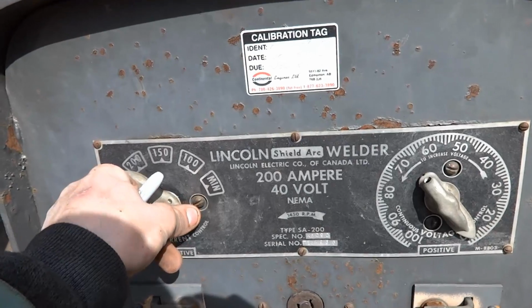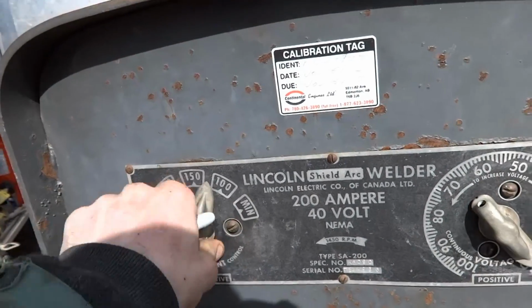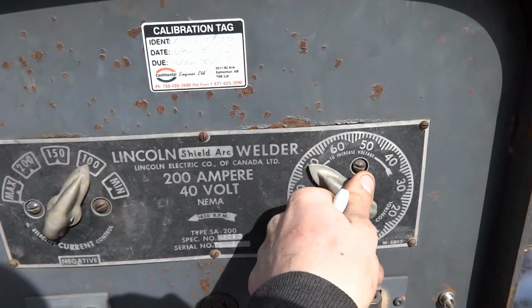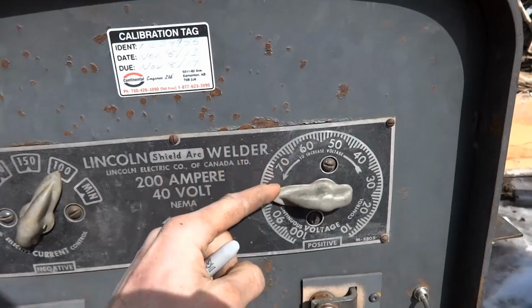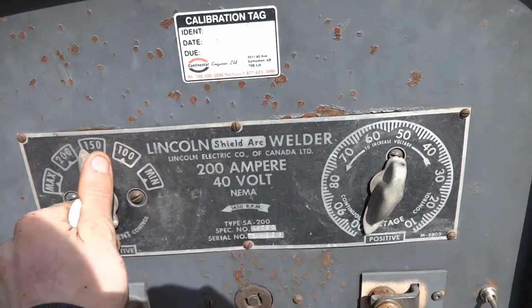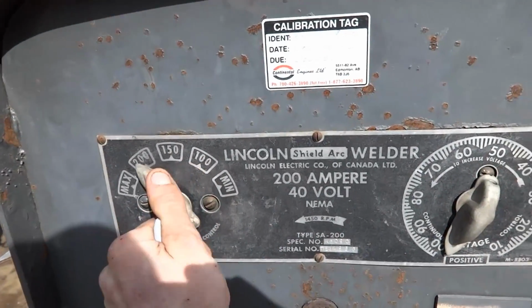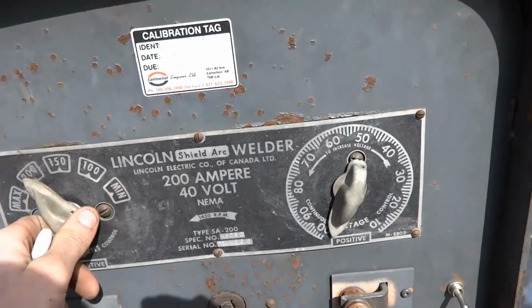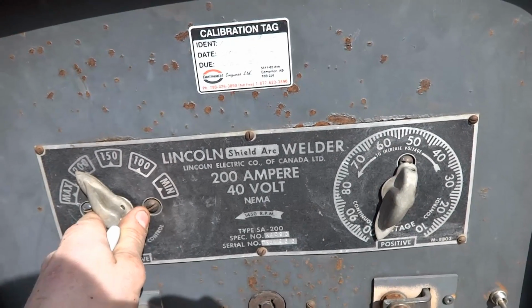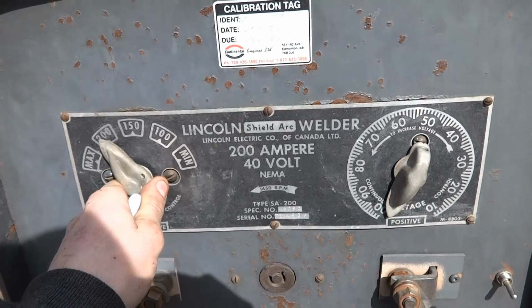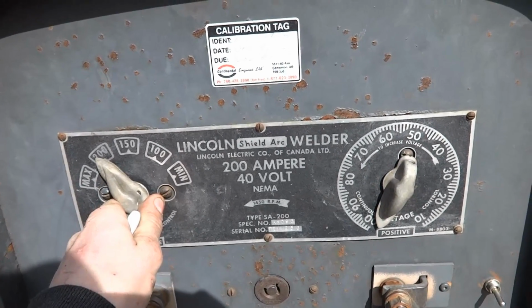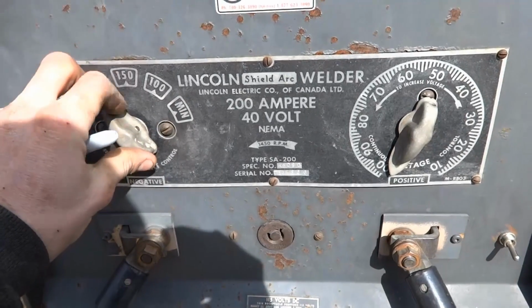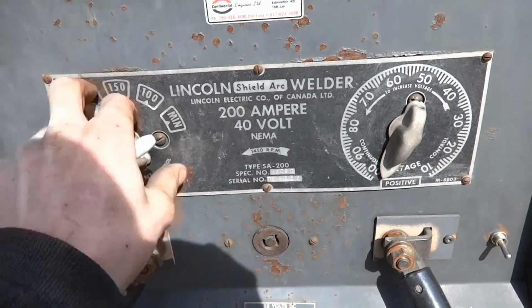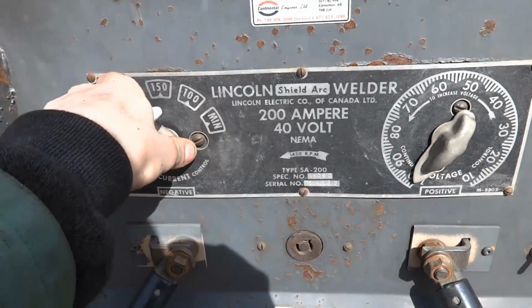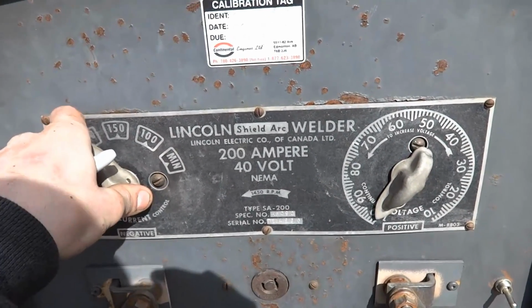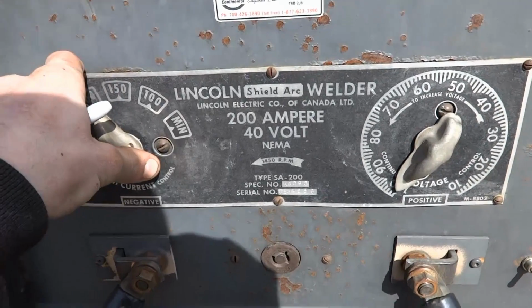Now when I say that, you look at some guys' remotes and their voltage is 70, 80, 90, 100, maybe third gear, 80, 90, 100, fourth gear, 80, 90, 100, and they're welding 7018, doing a vertical up weld. Say if they're your tag partner on, say, a heavy wall pipe, those guys are going to be screwed. The reason why is because they have a lot of voltage in the arc and lesser amperage. With more voltage in the arc and less amperage, the puddle is very soft.